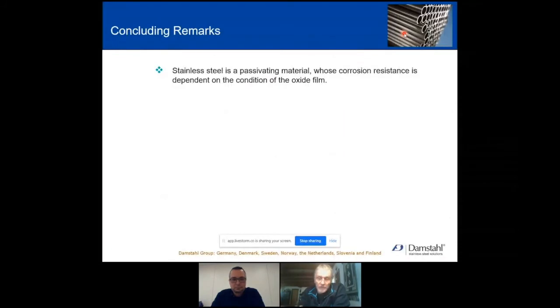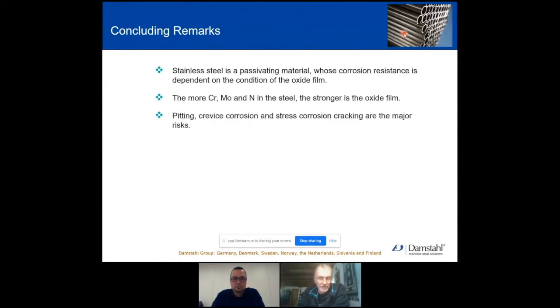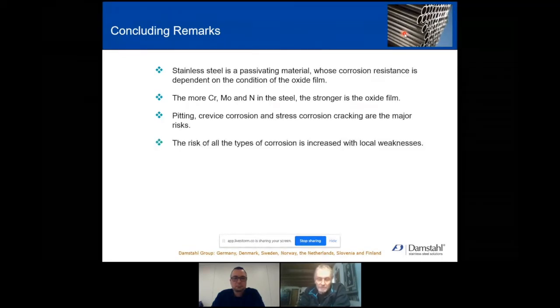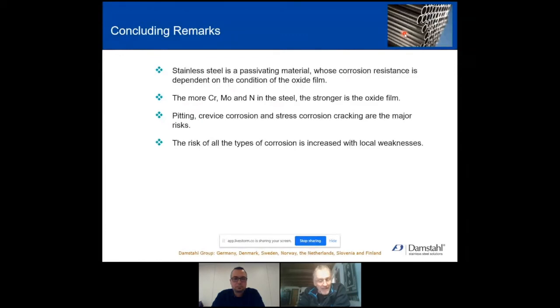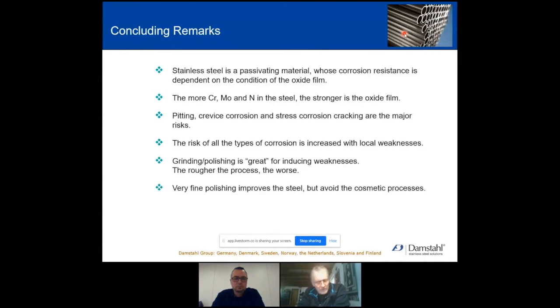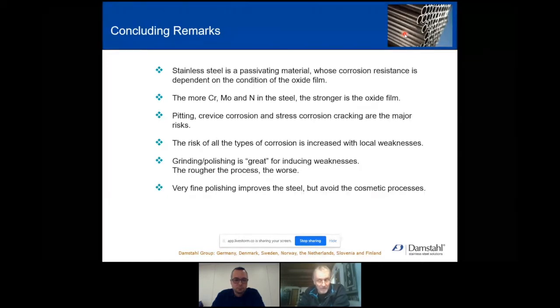So just to conclude, stainless steel is a passivating material. The more chromium, the more molybdenum, the more nitrogen, the stronger is the oxide film. Three major corrosion risks. Local weaknesses, no good. All kinds of grinding and polishing are really great for inducing them. So don't, if you can avoid it. Very fine polishing improves it, but otherwise avoid this. Go for the chemical ones, especially electro-polishing. I really like that one.